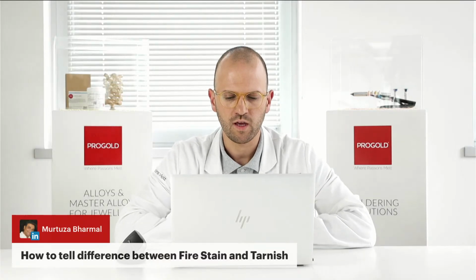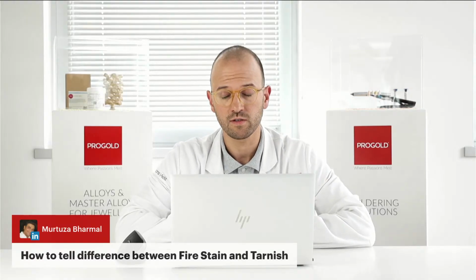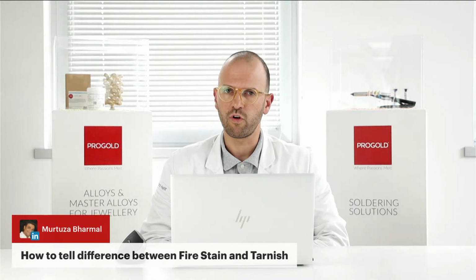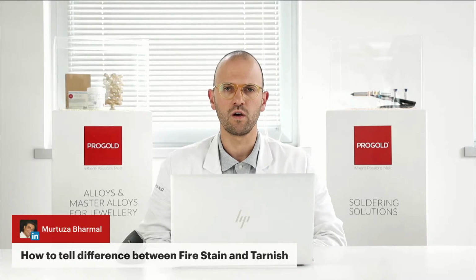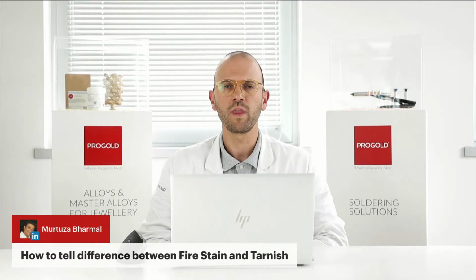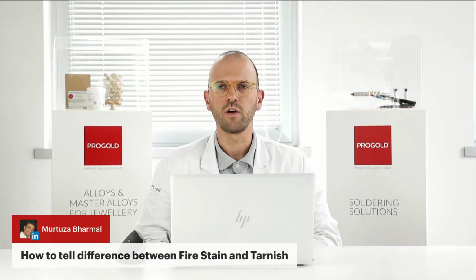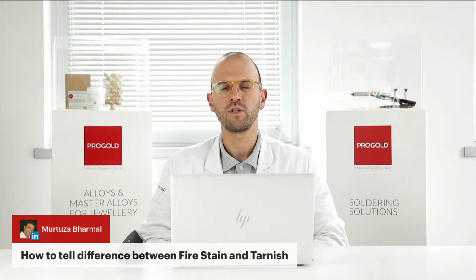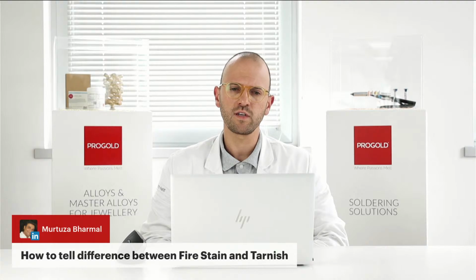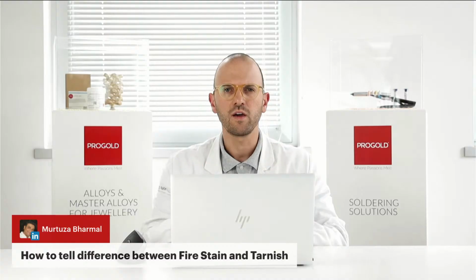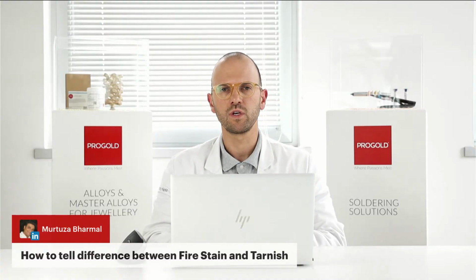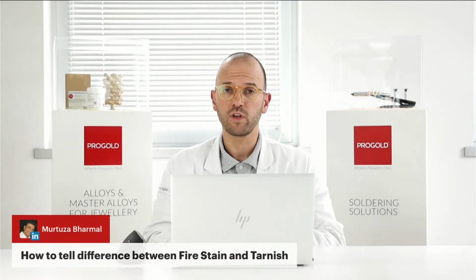Okay, Firestain and tarnish could be differentiated and recognized by their morphology through an optical microscope, but a scanning electron microscope could also help in order to understand the elements composing the surface. But first of all, through a morphology identification, it is possible to recognize them. In the case of Firestain, it appears like an opaque cloud over the surface, in the densest volume of the item where the solidification finishes, and generates copper oxide on the surface.